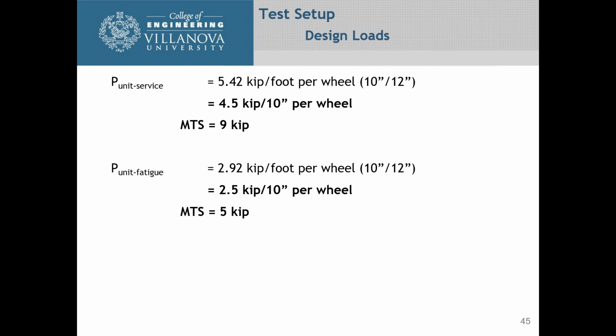So we had 2 loads that we were looking at. One was, we calculated out before, the load for service, and that was 5.42 kips per foot. And we're multiplying that by 10/12 because our beam sample is 10 inches wide. So you get 4.5 kips per wheel. And you do the same thing for fatigue, and you get 2.5 kips per wheel. So the MTS, which is the actuator, had to, for service, apply 9 kips, and for fatigue, 5 kips, because there's 2 wheel loads.